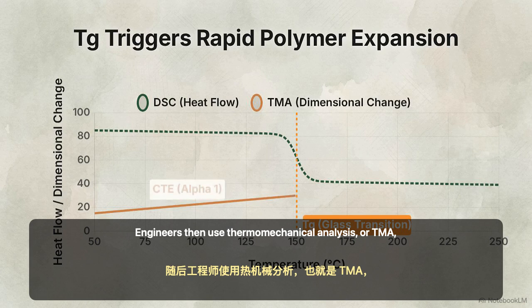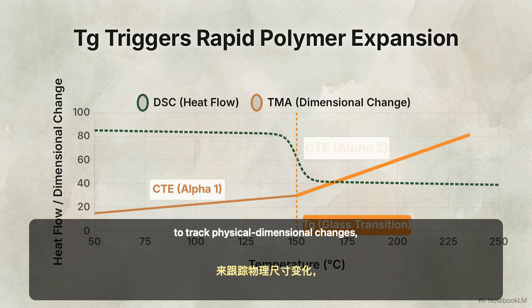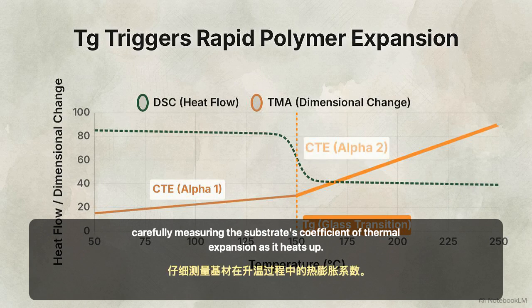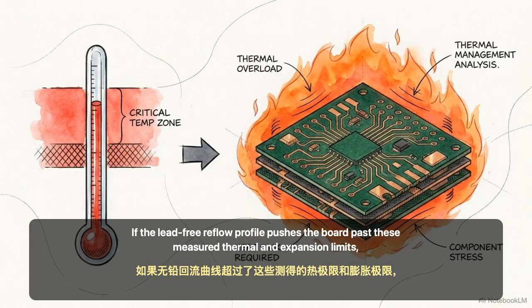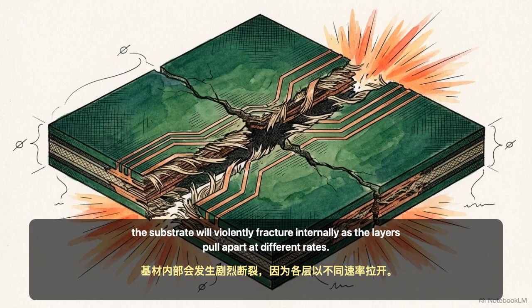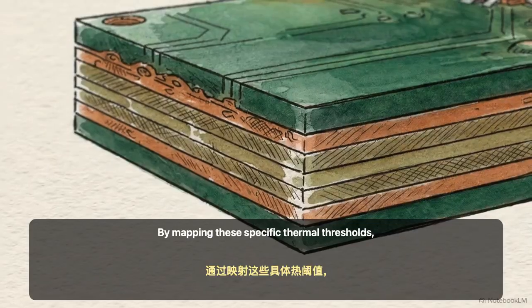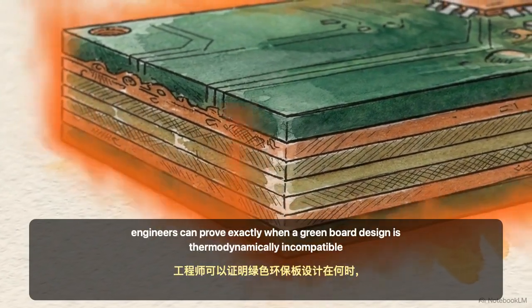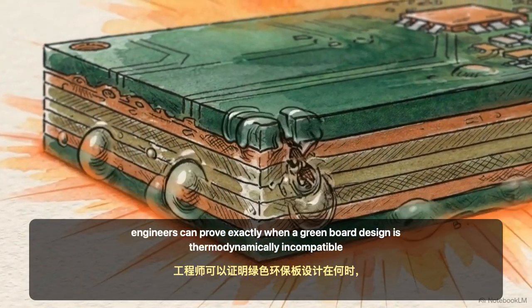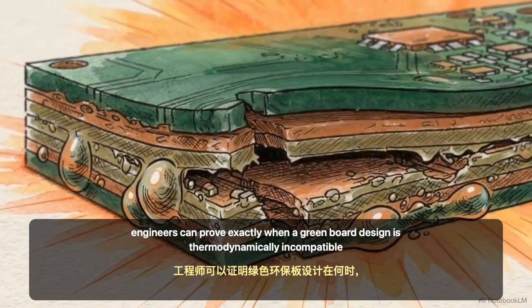Engineers then use thermomechanical analysis, or TMA, to track physical dimensional changes, carefully measuring the substrate's coefficient of thermal expansion as it heats up. If the lead-free reflow profile pushes the board past these measured thermal and expansion limits, the substrate will violently fracture internally as the layers pull apart at different rates. By mapping these specific thermal thresholds, engineers can prove exactly when a green board design is thermodynamically incompatible with its own manufacturing environment.